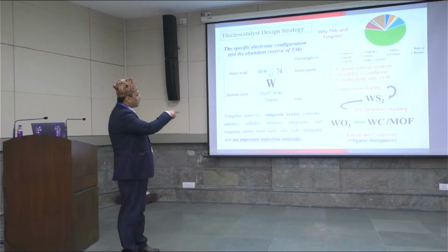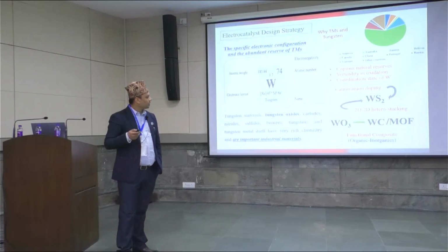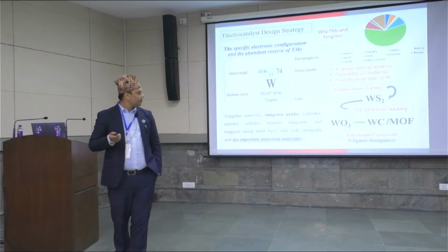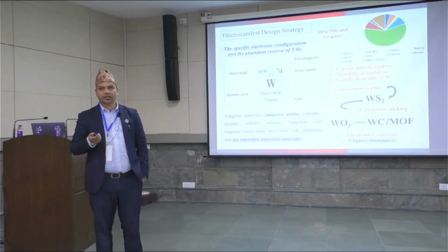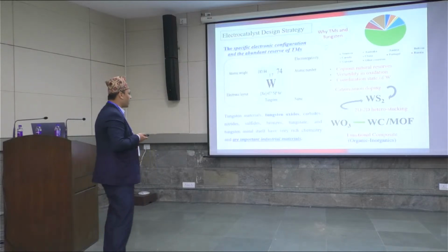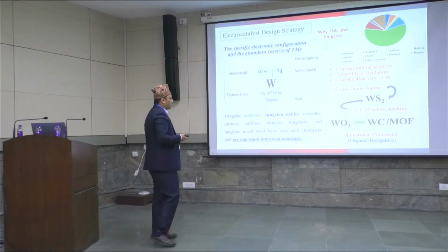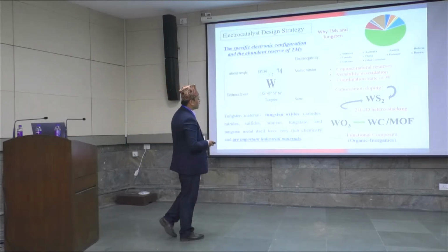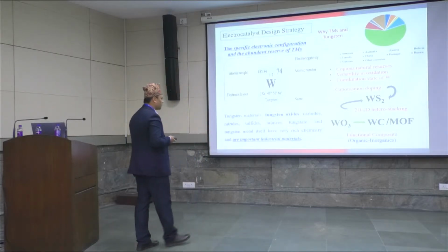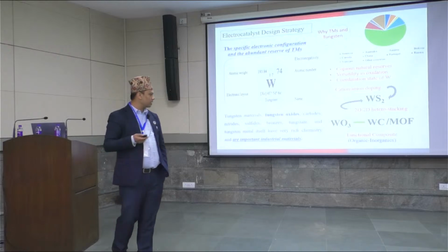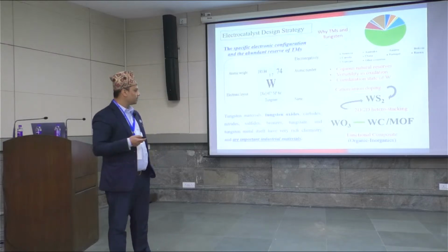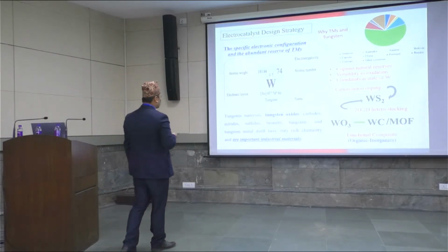Our strategy is mainly relevant to cation doping in tungsten disulfide, as well as a 2D heterostack with nickel telluride and tungsten sulfide, and later on we prepared a heterostructure of tungsten oxide with tungsten carbide and the MOF, which is regarded as a functional organic-inorganic composite.